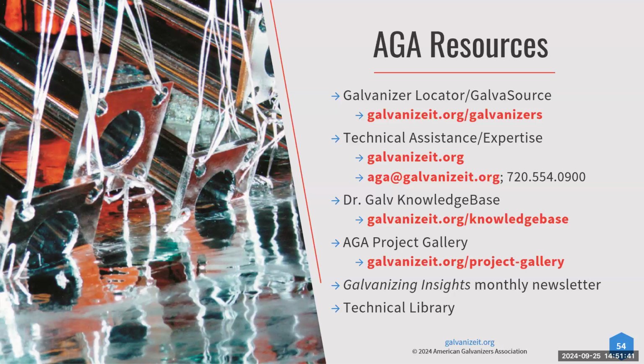All right. Tony asks, what type of welding wire or rod is best to use when galvanizing to minimize weld swelling after galvanizing? Sure, swollen welds. That's mostly from a high silicon or phosphorus weld rod. We'll get those swollen welds, so watch out for that. But mostly just matching the steel chemistry is best, because if you match the steel chemistry with your weld rod, you're going to have the same coating growth on the non-welded area and the weld. So watching out for that weld rod chemistry is probably the most important.